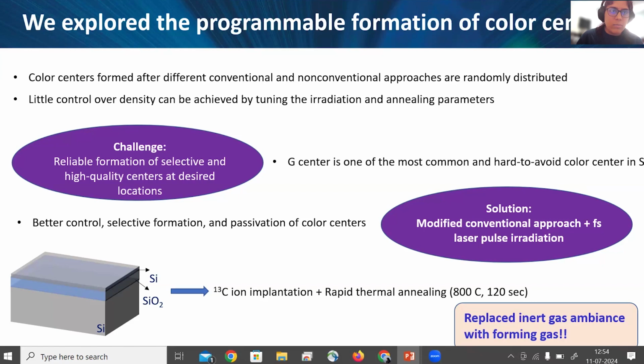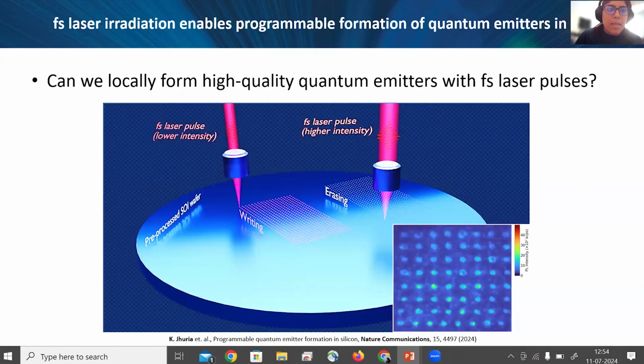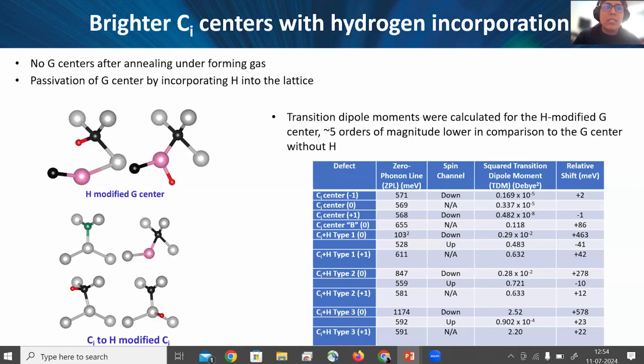And what it does basically is, maybe I'll first come here. What it does is it passivates the most commonly formed G centers. So when you have ion implantation and thermal annealing in inert gas ambience, you end up making the G center, which is a pair of two carbon atoms and a silicon atom. Now if you introduce hydrogen in its vicinity, the transition dipole moment of this color center, which in experimental terms is the intensity, drops by about 5 orders of magnitude. So you basically passivate this G center by introducing hydrogen in the lattice.